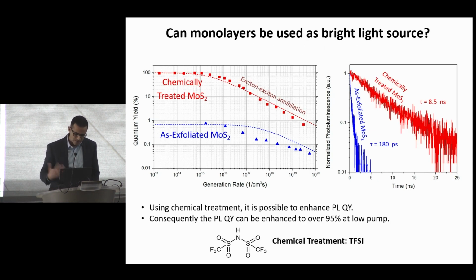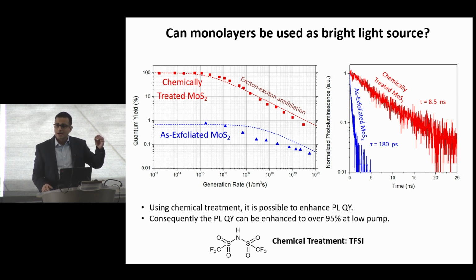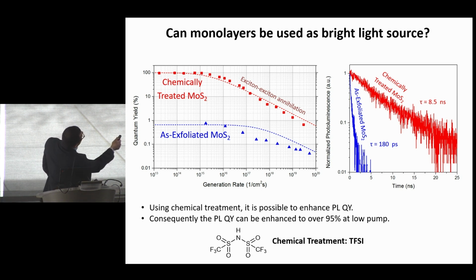We looked at various approaches to improve the quantum yield, and what we found was treating the monolayer with this molecule, and this molecule is called TFSI. It's a Lewis acid. It dramatically enhances the quantum yield to about 100% at low generation rates. So think about generation rates as the brightness level of the device, how many excited particles you're dealing with. What we really care about is operating the devices over here. But nevertheless, in the low excitation regime, we saw that the quantum yield was high.